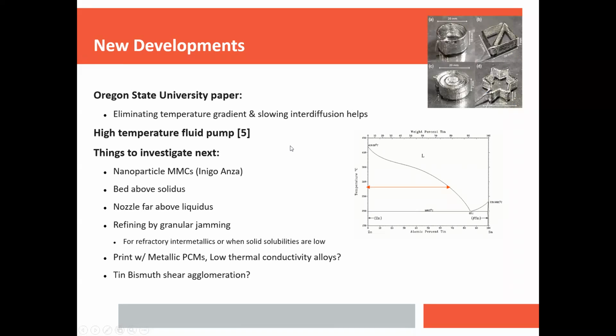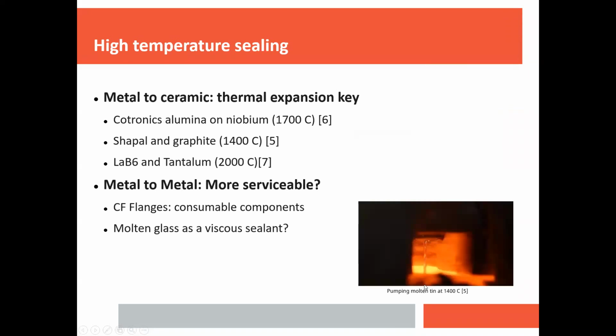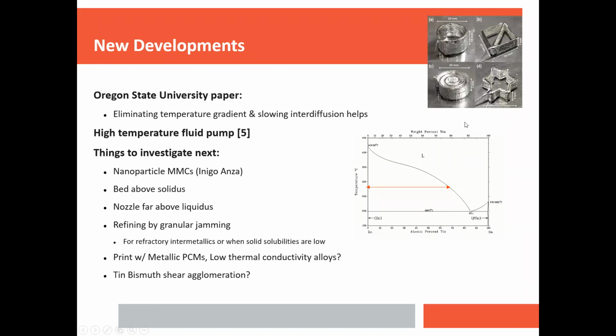MIT developed a high temperature fluid pump. I had a picture of it here, actually. They're pumping tin at 1400 C using Shapal and graphite here. They machine all the parts, and the thermal expansion coefficients are very similar. And that is, as far as I know, the record for highest temperature active mechanical pumping. Pumping liquid metals is not easy, especially at high temperatures. So there's a lot to investigate next.